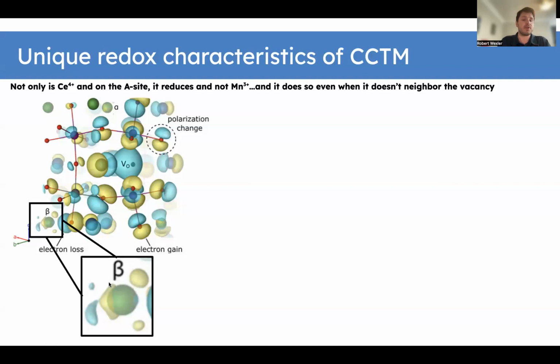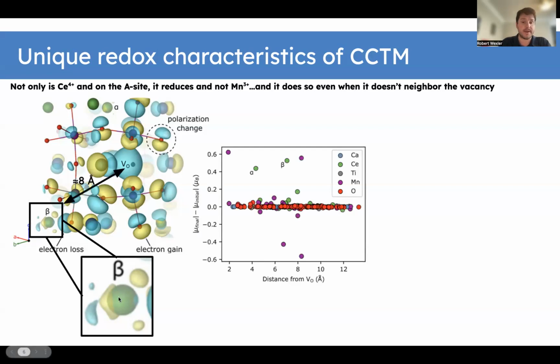gain of electrons, which upon vacancy formation means that those electrons produced by the neutral vacancy are actually going to ceria. And so if we actually look here, that's about 8 angstroms. It's quite incredible that the charge redistributes itself in a way such that most of the additional charge localizes on a neighboring ceria. So you can see here that on average, manganese shown in purple, as a function of distance from the vacancy, basically the change in their absolute magnetic moments, which tells us about change in oxidation state. There's about a net 0 change in the overall manganese and B site sublattice redox.